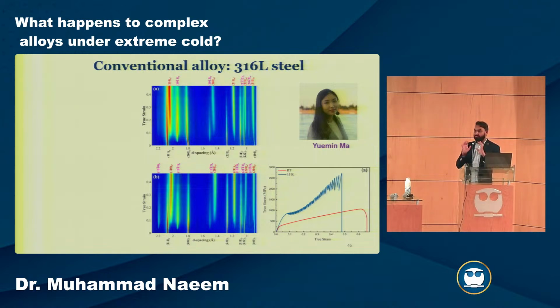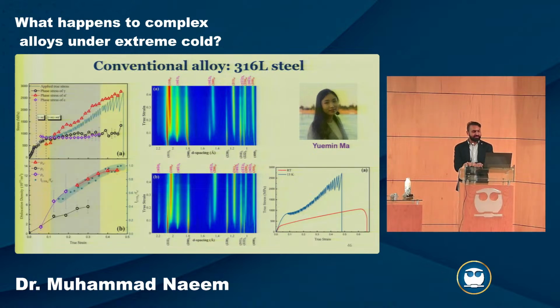So initially it was FCC, face-centered cubic, but then in the transfer section you also see HCP peaks like this epsilon phase, and also alpha prime, which is a BCT martensite phase. And then we can quantify the contribution of, now this is what Yuemin Ma also worked with, this heterostructure material, but this is a heterogeneous material, like a composite as well, because it has HCP, BCC, FCC, and in this you can see which one is contributing more towards ultimate stress.